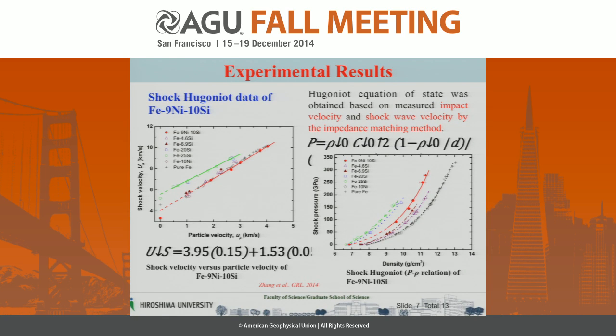This is our experimental results, and this is our measured shock Hugoniot data of our sample. This Hugoniot data is based on our measured impact velocity and the shock velocity of the sample by the impedance matching method, from which we get the shock parameters. Our results are consistent with the previously determined iron-silicon by shock. Compared with the previous iron-nickel and iron-silicon systems, we know that adding nickel into the iron-silicon does not affect the density at high pressures significantly, and our results are consistent with the iron-nickel system.